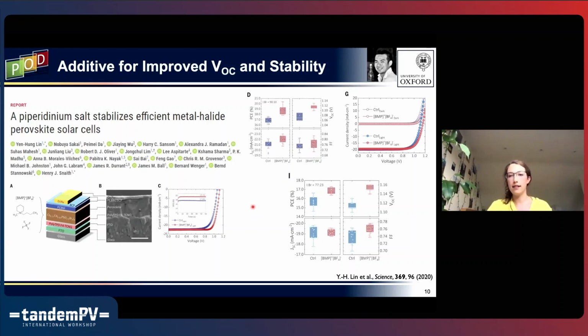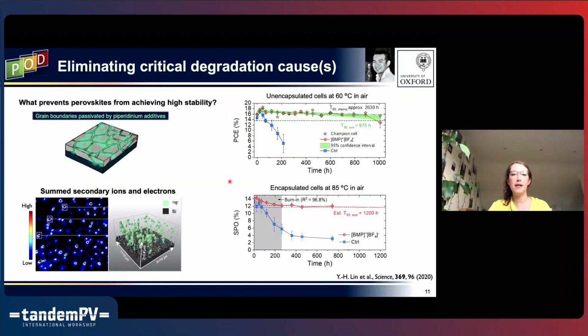But we see this improvement basically in the overall efficiency, which is great. But the really neat thing about this additive is that we get really good stability of the perovskite material. So if we look here, just a control device, these are just PIN devices with the FA cesium. We can see how the control device, especially unencapsulated control devices, die fairly quickly. And this is just at 60 degrees, so we're not even at 85 yet, versus the perovskite with the piperidinium added in actually have this really good stability over time.